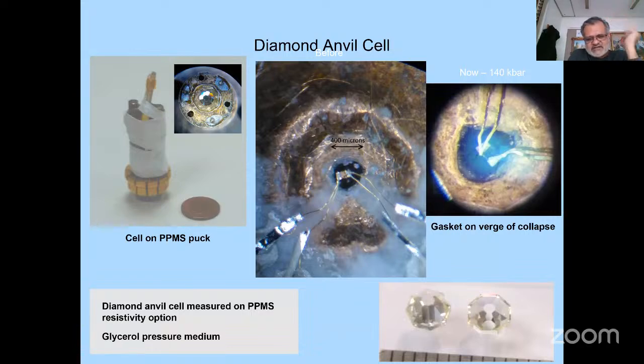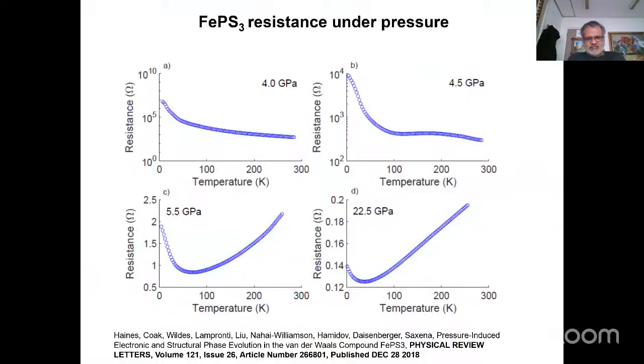We use diamond anvil cells, and we can reach, in our case, a little around 300 kilobars, 30 GPa, and we're able to do transport measurements on them, also a little bit of magnetization, but largely neutron and synchrotron measurements as well. So the initial measurements showed that if we compress FePS3, iron PS3, which is sort of an activated insulator at low pressures, it starts to give way as we increase pressure, and resistivity starts to become more and more metallic type with this interesting low temperature behavior, which we'll come to in a second.